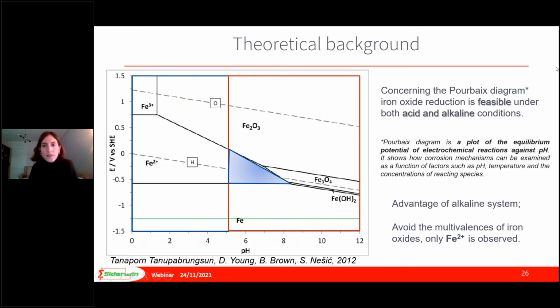To investigate the feasibility of every electrolytic process, a Pourbaix diagram is essential. It is also known as a potential-pH diagram and is a plot of the possible thermodynamically stable phases of an aqueous electrochemical system. Concerning the Pourbaix diagram for iron oxide, it seems that the production of metallic iron is feasible under acid and alkaline conditions from -0.55 volts versus standard hydrogen electrode. The alkaline system has the important advantage of avoiding the multivalencies of iron, with the presence only of the divalent iron cation.